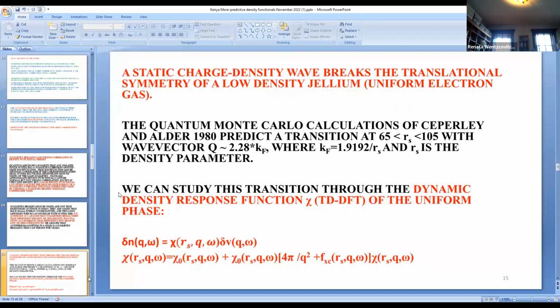The basic idea here is that we have a uniform density, and we apply a weak perturbing external potential delta V, which is a wave with a wave vector Q and with a frequency omega. We get a density response, delta N, that is proportional to this weak perturbation. The proportionality constant is this density response function chi, which is a function of the density or the RS parameter, a function of the wave vector, and also a function of the frequency.